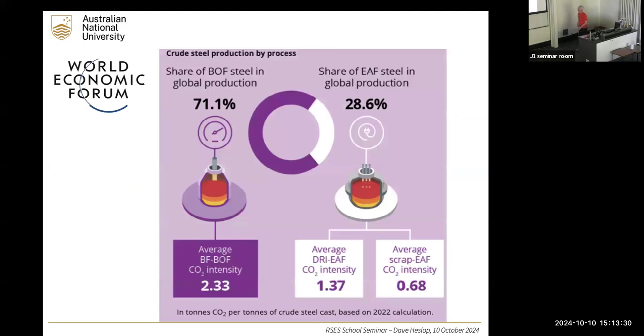So again, this is from the World Economic Forum, just thinking about these two pathways. The pathway along the top, where we've got coking coal in the blast furnace versus direct reduction along the bottom. 70% of the steel produced globally is through this blast furnace, basic oxygen furnace route. That's the top route. And then we're talking about CO2 emissions of 2.3 tons per ton of steel. So again, this is the really fossil fuel heavy route, the one that is dominant in terms of iron and steel production. The alternative pathway along the bottom, which was direct reduced iron and electric arc furnace, CO2 intensity is lower, 1.4 tons per ton of steel, but that's only about 30% of production.